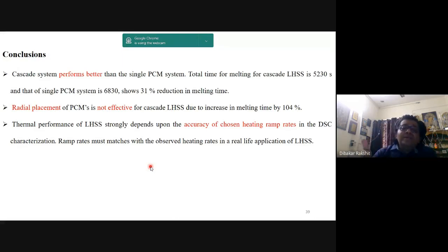But when we are speaking about the placement, whether it is to be done longitudinally, circumferentially or radially, the radial placement was found to be not so effective due to the increase in the melting time, and that melting time was quantified to be increased by around 104%.